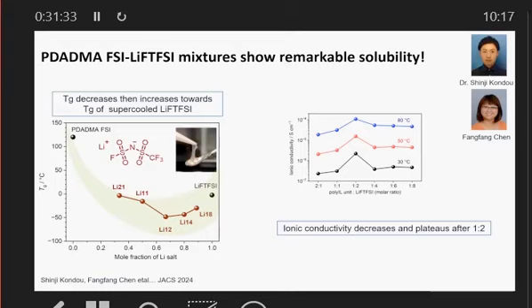So in other words, when we look at the effect of salt on the Tg of the system, it doesn't always go down. It depends on what the Tg of that final salt is that you've got in there. So there's not a straightforward correlation between Tg and salt composition necessarily. What was a surprise to us, though, was that the conductivity behavior had this same maximum at 1:2. It's like, well, why? We want to get past it. We want this to go higher. We want higher conductivity, and yet we reproducibly found that the 1:2 gave us the highest conductivity by a long way, almost a factor of 10 increase here, which when you look at the Tg was a surprise because the 1:2 and 1:4 aren't that different in Tg. So it can't just be the Tg that's causing this effect, right?